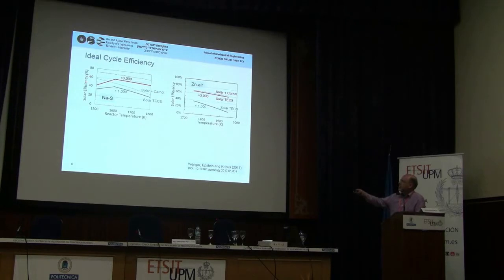The conversion efficiency, or the solar efficiency, when we also consider the fact that this reactor is exposed to concentrated solar energy, so the aperture of this reactor will radiate energy into the environment, and this is also an additional loss that cannot be avoided. So if we concentrate radiation by 1,000 times, we can get efficiency overall of about 40-something percent. If we concentrate 3,000 times, which is not simple, but it can be done, we can get efficiency of 60% on the overall conversion between entering solar radiation and exiting electricity.